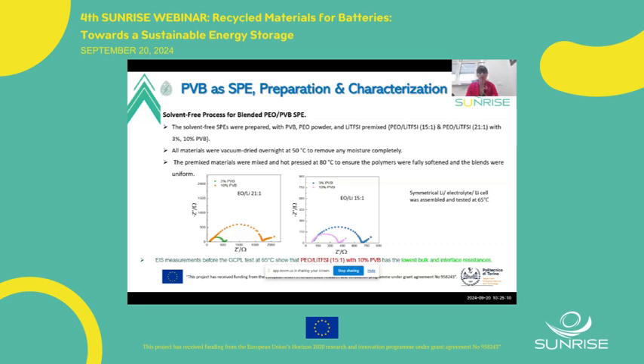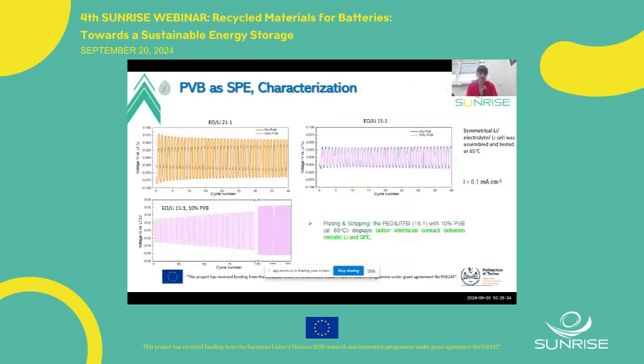The PEO-lithium 15:1 with 10% PVB, the purple one, shows the lowest bulk and interface resistance. So in terms of impedance, we understood that 10% PVB with PEO-lithium 15:1 is the best percentage, showing the best promising performance.